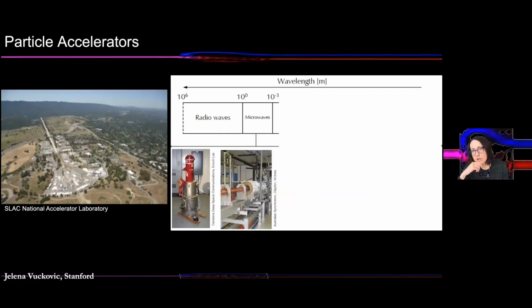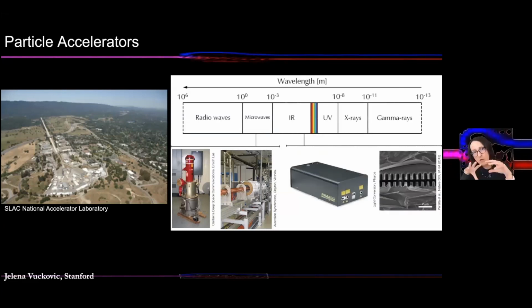And this work is really inspired by ideas of my colleague Bob Byer, who has been thinking about this for decades. And it's really a very simple idea. State-of-the-art accelerators use microwaves or radio frequency waves to accelerate particles. But these waves have wavelength, the separation between crests of electromagnetic waves, that is about 10,000 times larger than for optical waves. So if we could use a different spectrum of electromagnetic waves, with shorter wavelengths, to do the same function of accelerating particles, we should in principle be able to shrink the size of the accelerator.